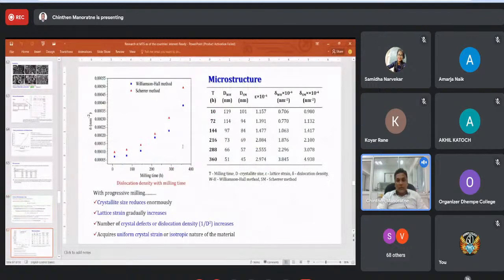Now you can see that the microstructure has been changing because of this ball milling, and the crystallite size reduced enormously. The strain is gradually increasing. We calculated these things using both methods, the Scherrer method and the Williamson-Hall method. And after 360 hours, we observe uniform crystal strain and isotropic nature of the material.